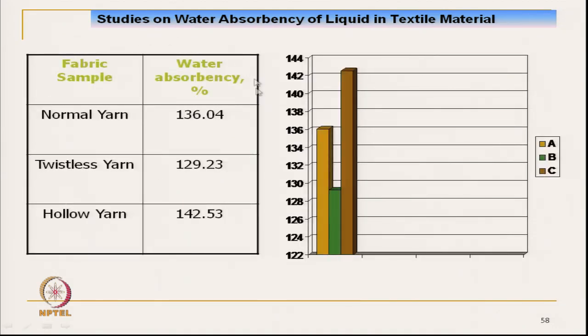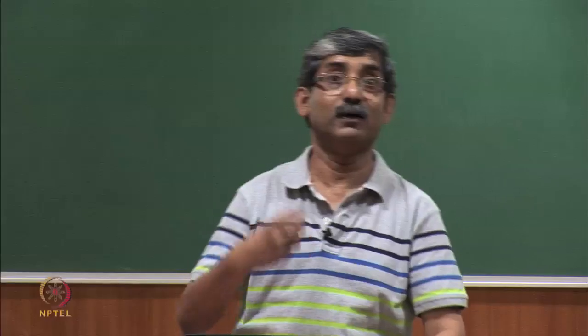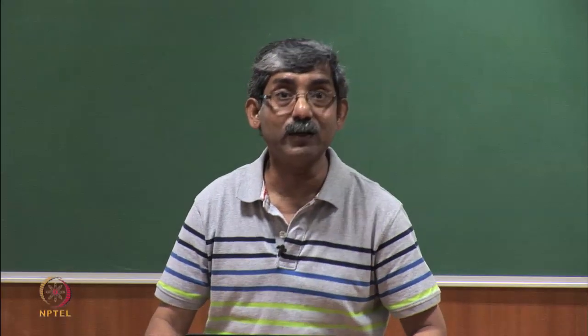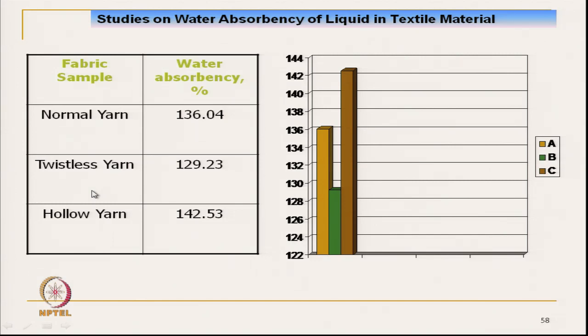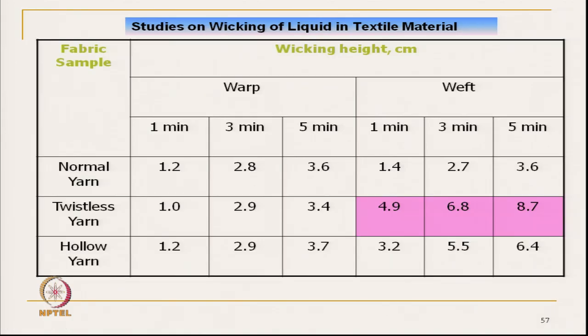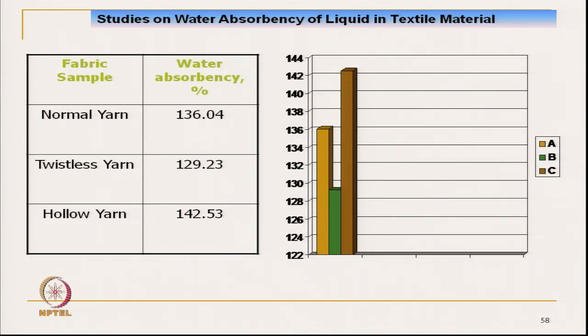Similarly, absorbency is high when the pore volumes are high. Here we are not talking about wicking. Hollow yarn, which has very high pores, has very high absorbency. It absorbs well due to the pores, but it cannot wick as well as the twistless yarn, because due to the larger pores it cannot create the capillary pressure. That is why its wicking height is less.